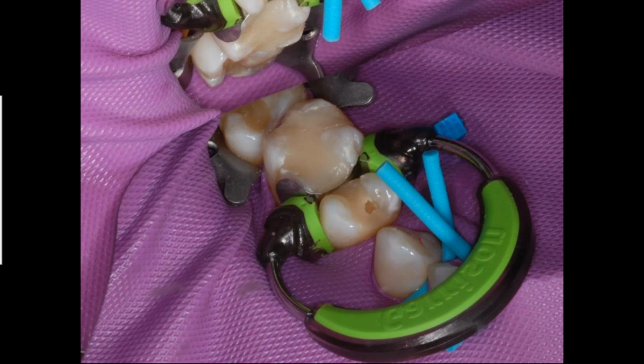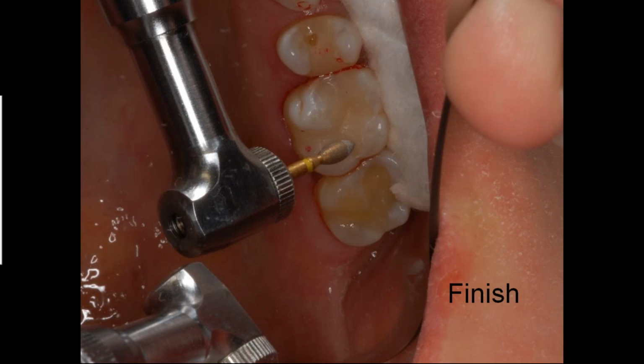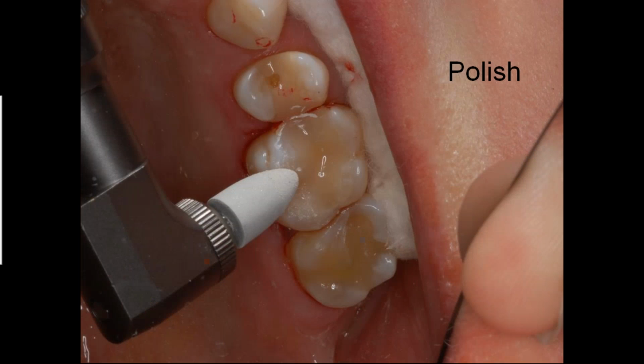And then finally the buildup and final curing of 20 seconds of our restoration. Now we're going to go ahead and remove the ring and sectional matrix and our wedge. Do our finishing and polishing. I'll talk about that. When this was done a few years ago, I was using fine diamonds, extra fine diamonds. Fine diamonds were 45 micron grit. Extra fine are about 15 or so, 20, and you'll see how I've changed and improved on this approach. Back then, this was a nice way of going ahead and reducing some of the excess composite, adjusting the occlusion. It's a little bit easier to do it with some of the fluted carbides you'll see, and less potential negative effects on the enamel. Then we finally do our polishing.